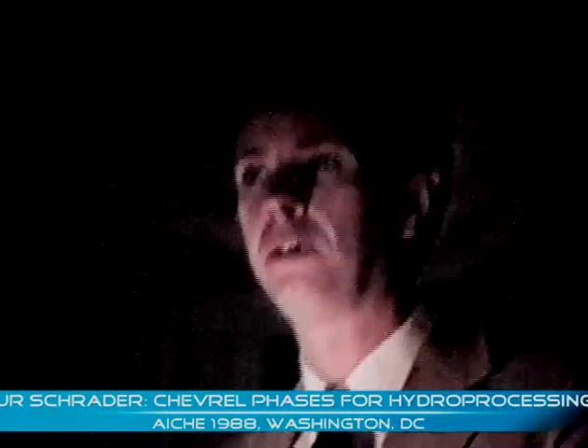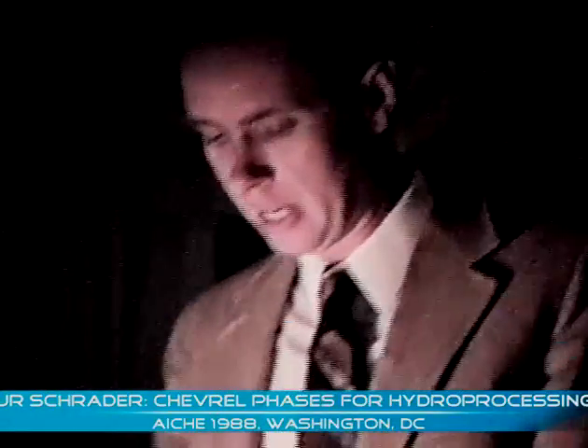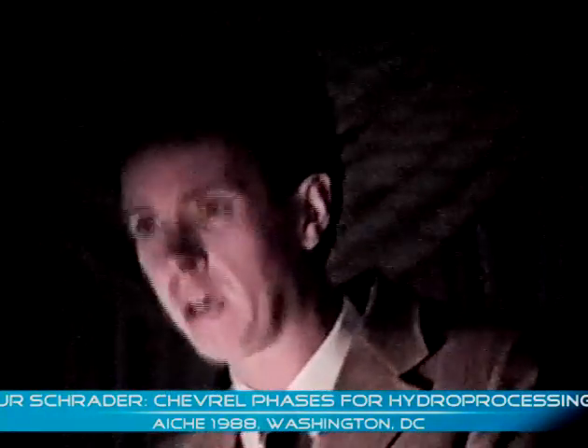We became interested a few years ago in looking at a new class of hydrodesulfurization catalysts based on so-called reduced molybdenum sulfides. These are based on compounds that were discovered by Professor Roger Chevrel of France, who was initially interested in their superconductivity properties. But the reason we were interested in them is that as reduced molybdenum sulfides, they emphasize the electronic properties of these catalysts. Because there was such a rich chemistry involved, there was the opportunity for varying some of the electronic properties of these materials and perhaps correlating this with catalytic activity.